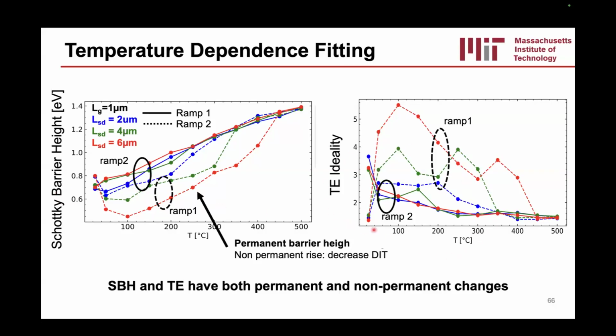And similarly, we can look at things like the ideality factor and once again see that in the ramp 1 case, it's very large, but in the ramp 2 case, it reduces significantly in a permanent manner, and once again, still decreases as we increase the temperature. And so both the Schottky barrier height and the ideality factor have permanent and non-permanent changes, potentially associated with things like trapping, which are non-permanent, and metal diffusion into the gate, which would be permanent.